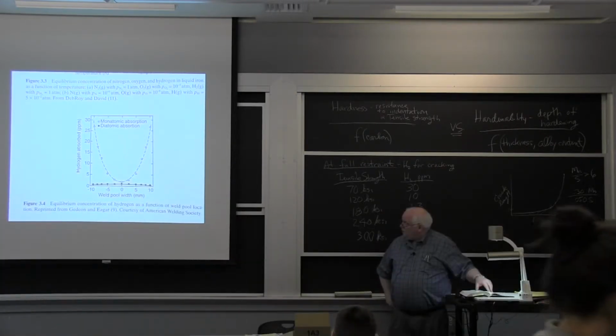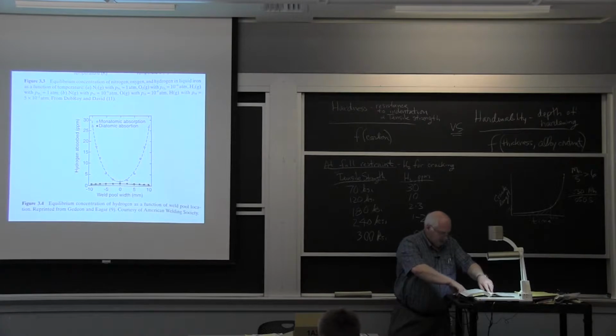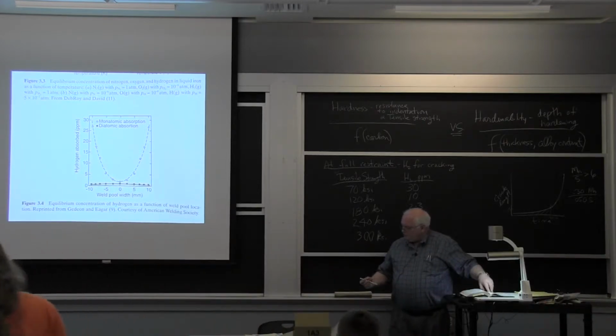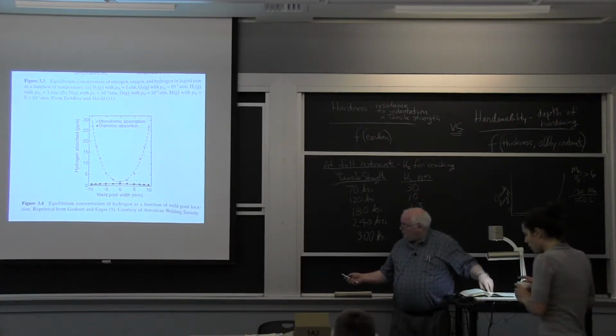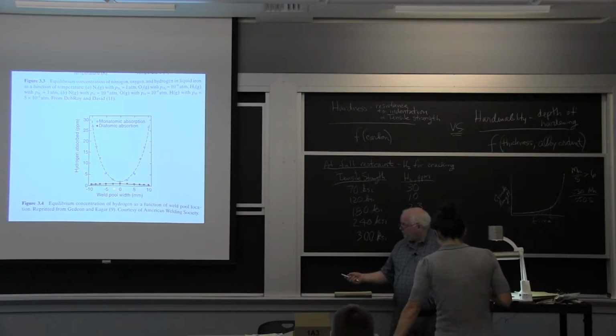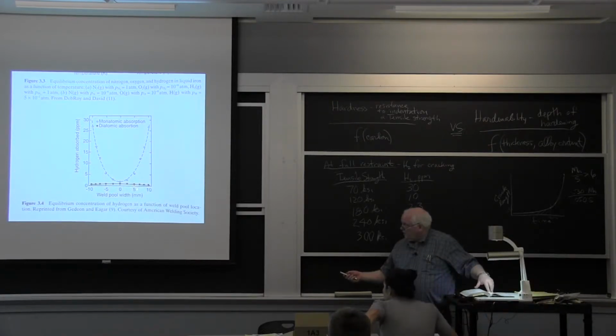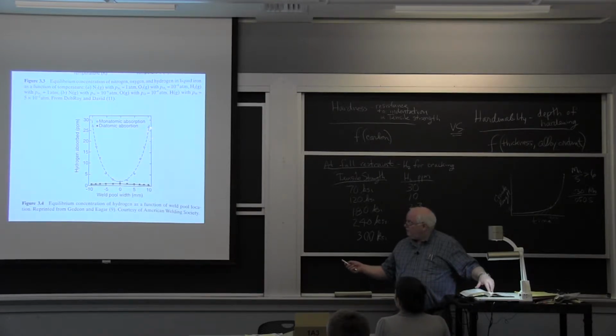Here's a plot of monatomic hydrogen and diatomic hydrogen and how much gets absorbed in different parts of the weld pool. This is the weld pool width in millimeters, so you're talking a centimeter on either side. And this is just a theoretical calculation for diatomic hydrogen. It doesn't really absorb very well in the weld pool, but thermodynamically, in the cooler parts of the weld pool, monatomic hydrogen goes in and gives you your 30 parts per million. So it turns out it's monatomic hydrogen.